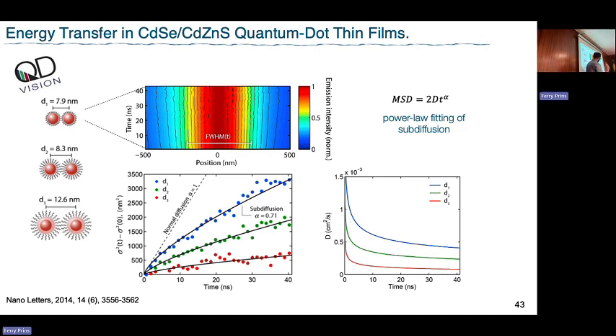The one thing that's important to realize with this kind of subdiffusive behavior is that in the beginning we're moving fast and then we slow down. Here you plot basically the first derivative of this fit, where you see that everything starts off fast and gets slower and slower as time goes by.